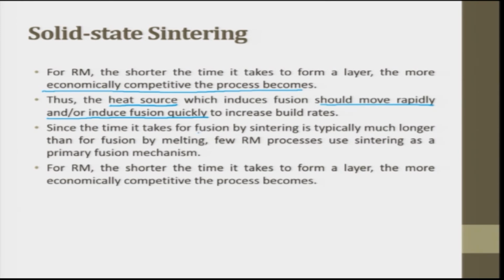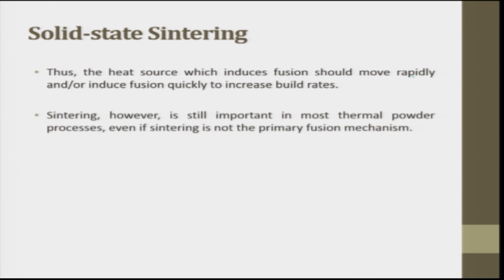Since the time it takes for fusion by sintering is much longer than fusion by melting, few RM processes use sintering as the primary fusion mechanism. For RM, the shorter the time it takes to form a layer, the more economically competitive the process becomes. Thus, the heat source which induces fusion should move rapidly, inducing fusion quickly to increase the build rate. Sintering, however, is still important in most thermal powder processing, even if it is not the primary fusion mechanism.